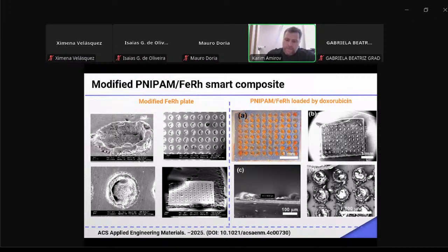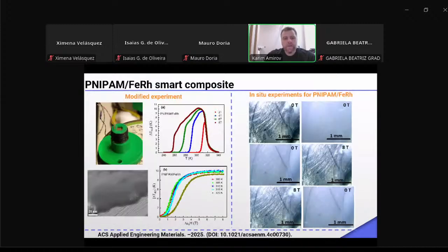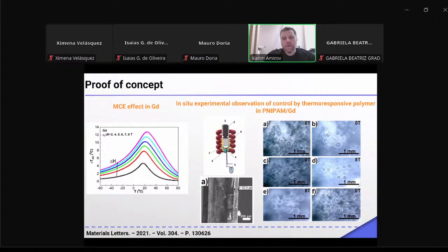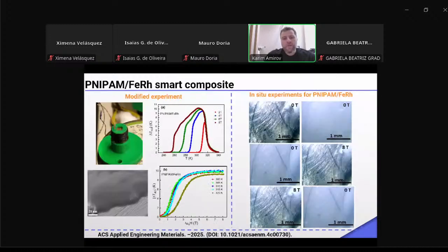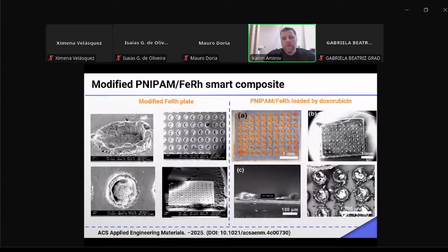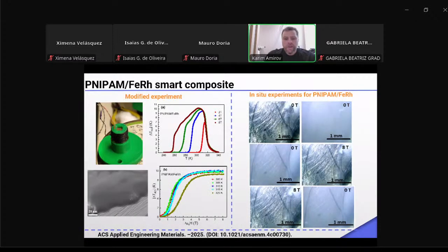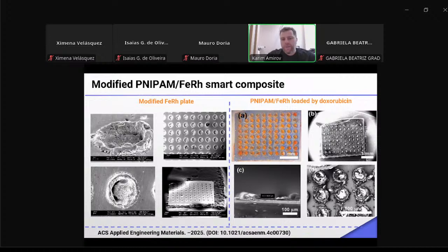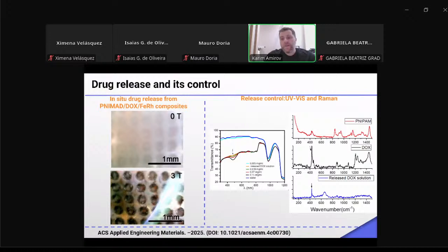So for this task, we use this modified insert with this one camera, and the protocol was the same, but specially here we hold our sample at about 36 degrees, close to human temperature. Apply 3 Tesla magnetic field, not 8 as we used before, but in the developed version we use 3 Tesla, because 3 Tesla is available in commercial MRI tomograph sources. And as you can see, the doxorubicin is successfully released.